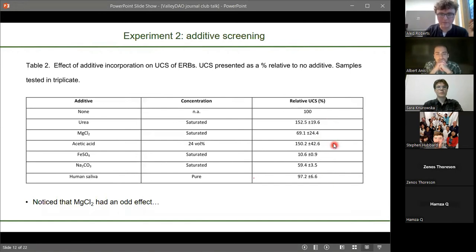And we found adding urea helped, adding acetic acid seemed to help. Adding magnesium chloride didn't help, but it had an odd effect, so it made it a lot sticky and slimy. So we thought maybe we've just used way too much because this was a saturated solution. So we incorporated that into the design going forward.